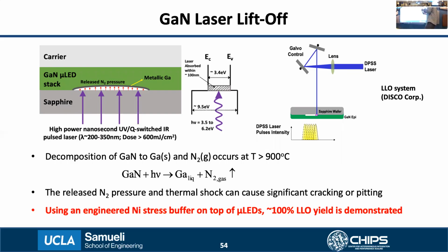The absorbed light is converted to heat and the temperatures can rapidly rise to more than 900 degrees Celsius. When this happens, the gallium nitride dissociates into liquid gallium and nitrogen gas in a process called ablation. This is a very high stress process because of the released nitrogen pressure, created because of the gas absorbing the heat. There are also significant transient thermal gradients at the interface, which induce significant stresses on the films. A combination of both of these mechanical stresses can often cause cracking of the GaN films.